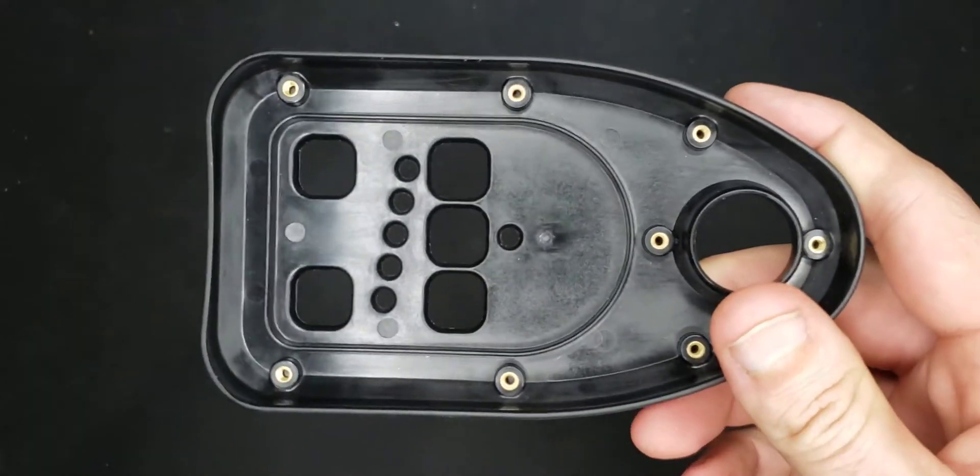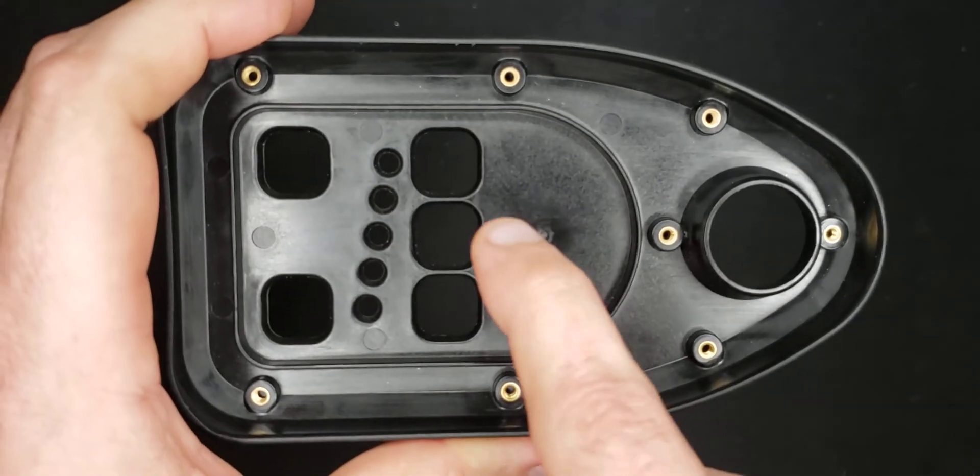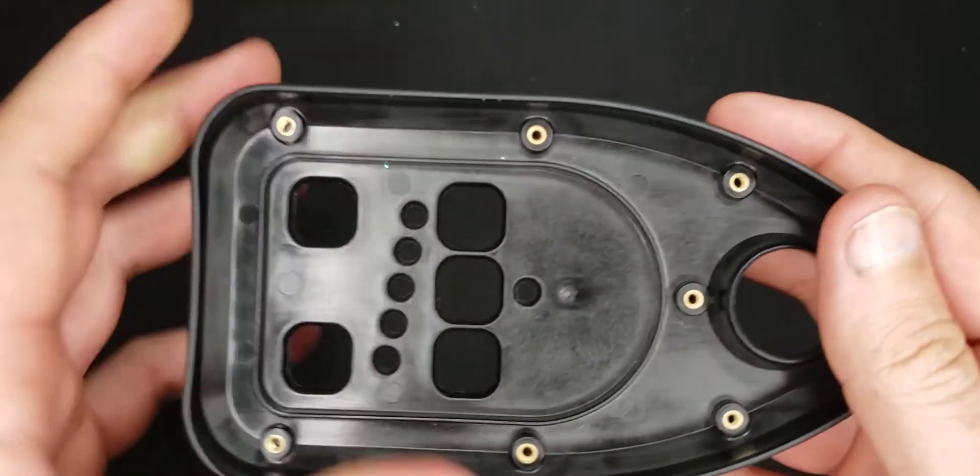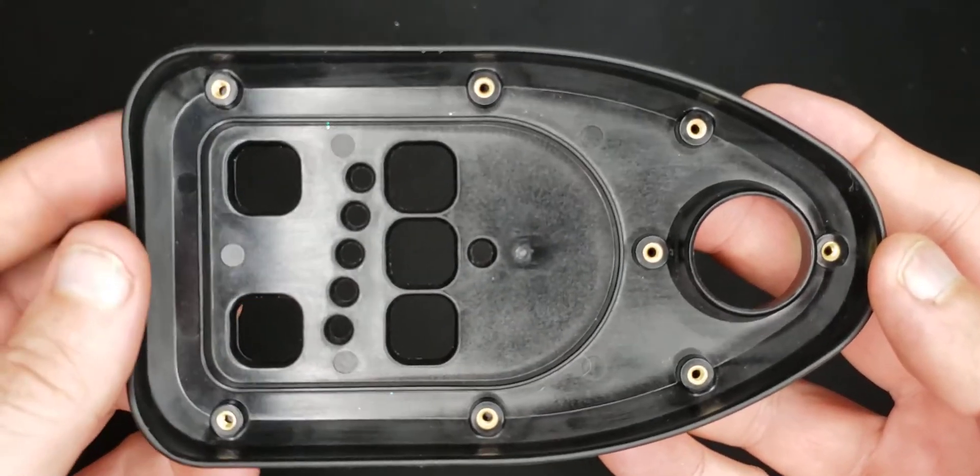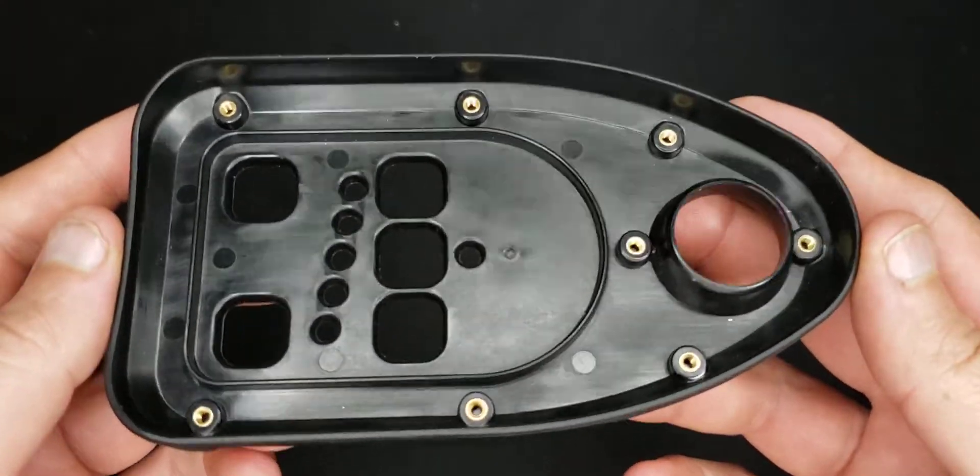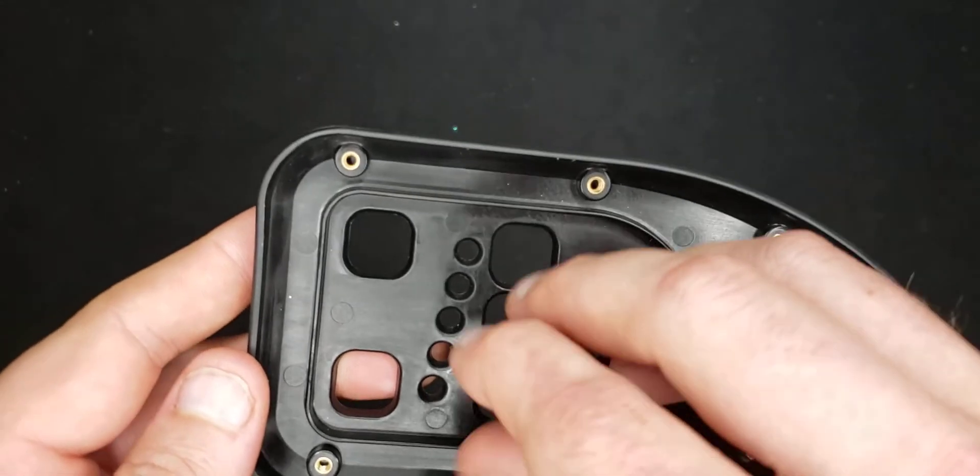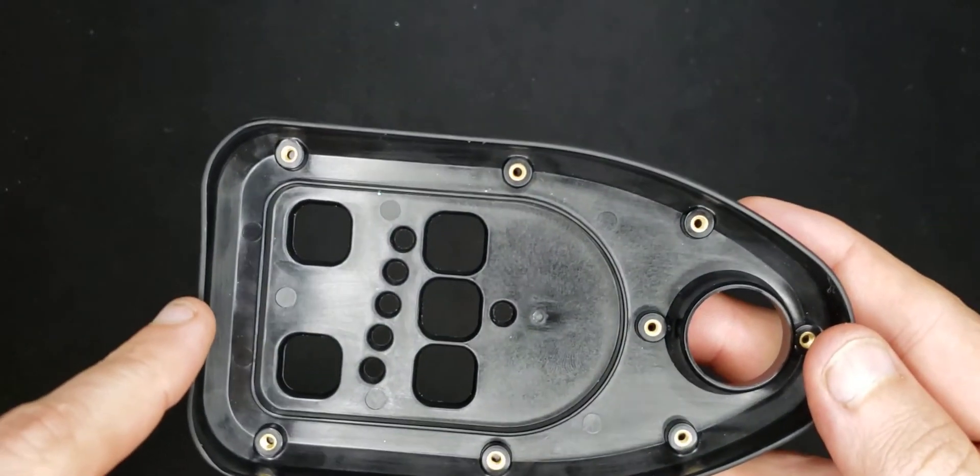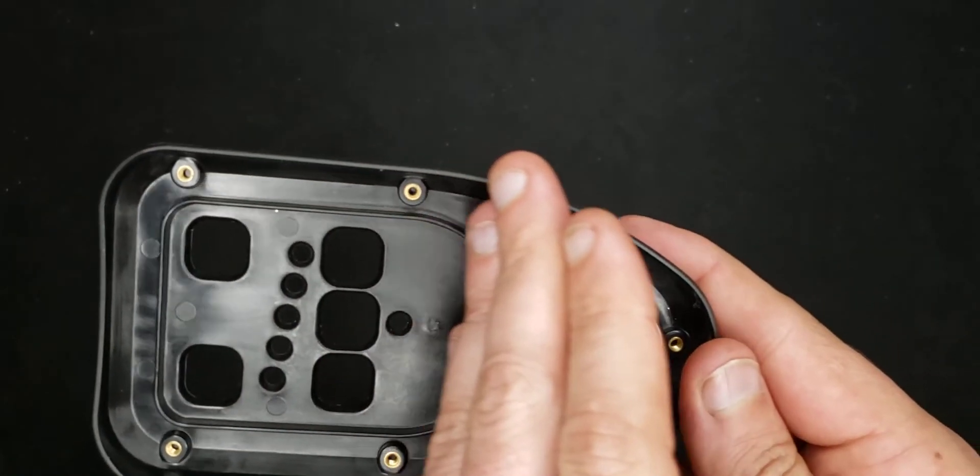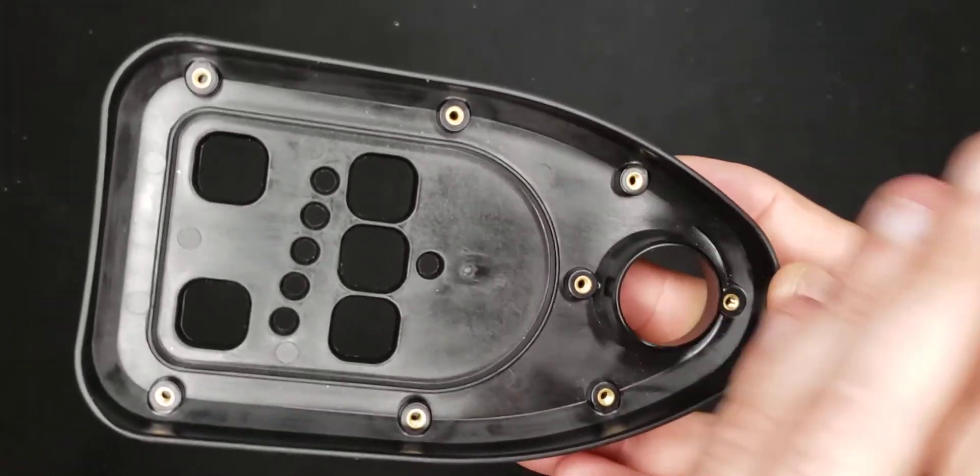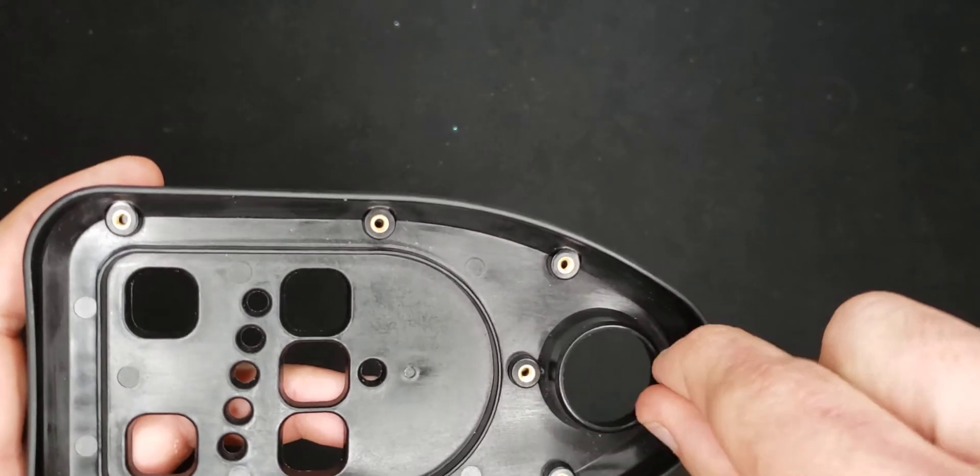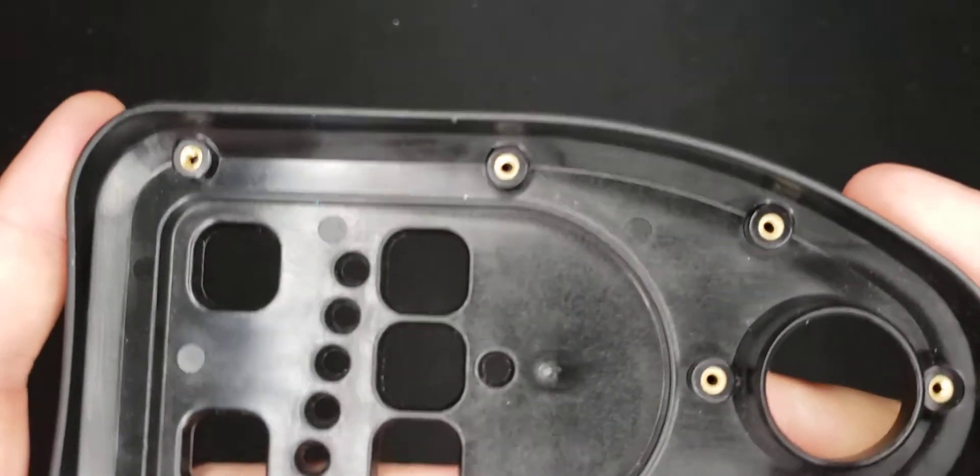Another consideration about gate location is I really like central gating. And that's because from the end product standpoint, you get more uniform distribution of material properties because the mold is really getting filled kind of symmetrically instead of starting over here. And so the beginning, your properties kind of change as the melt front degrades and gets cooled. And then by the time the plastic wraps around this pin right here and comes together, it really doesn't want to have as much strength where the material comes together.